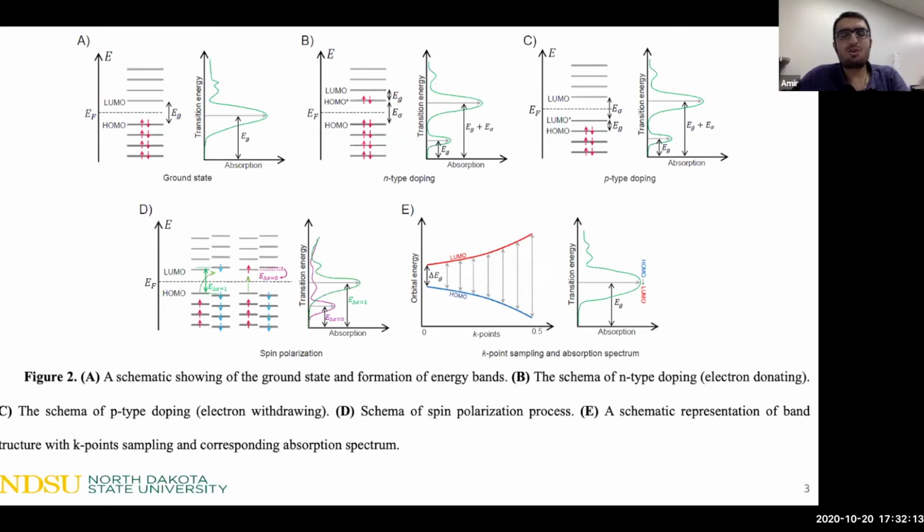Let me contribute to the discussion. I'm going to give a comment about molecules which are not conjugated and periodic. If a molecule absorbs well but does not emit, it could be a signature that upon excitation from singlet to singlet, it flips the spin and stops emitting, because emission from triplet is less efficient.